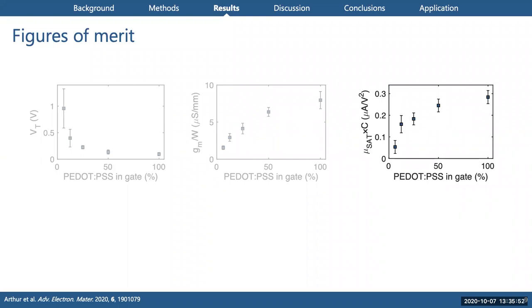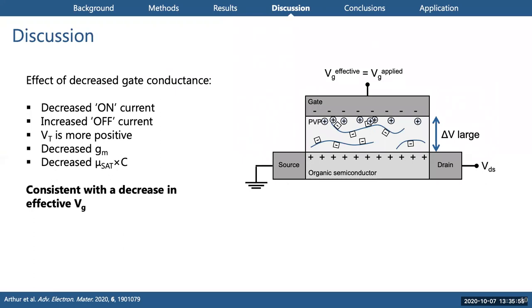Finally, we have the product of mobility and capacitance, which is a good overall measure of device performance, especially when we don't know what the capacitance is or the capacitance might be changing. Again, we see this familiar trend of improvement with gate conductance, finally approaching a plateau at a higher conductivity. In summary, from this small survey of the data, we see decreasing gate conductance is causing a decrease in the on current.